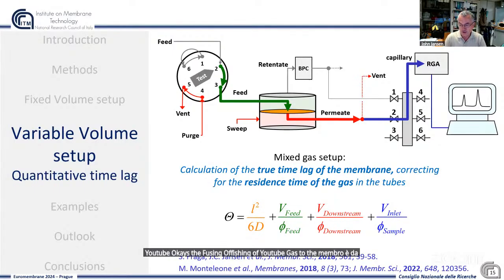And that's still not unique, but if you have a mixture and you measure with a mass spectrometer, you see both gases. You know what you feed, you see what you get out of it, and you can see the time dependence, the transient phenomena of both gases in the system, and from that you can calculate the diffusion coefficient of two gases that move at the same time through a material. And you understand how they influence each other, because very often they influence each other. That can be positive or negative.